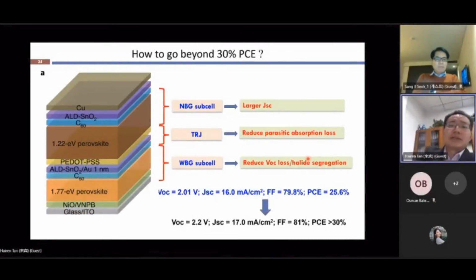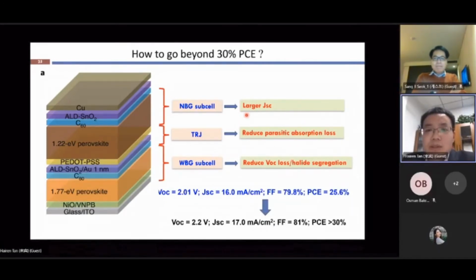But still, we are thinking about how to increase the efficiency beyond even 30%, or at least comparable to the efficiency of perovskite-silicon tandems. In the previous work, we mainly focused on the narrow band gap subcell, so we haven't carried out much work on the wider band gap perovskite material, and the VOC losses in this subcell are still quite high. The current density is also not high enough. That is mainly limited by the narrow band gap subcell and the parasitic absorption losses in the tunneling recombination layer. For example, if we can further increase the open circuit voltage and slightly increase the short circuit current density, I think we will be able to achieve efficiency above 30% in the coming two or three years.